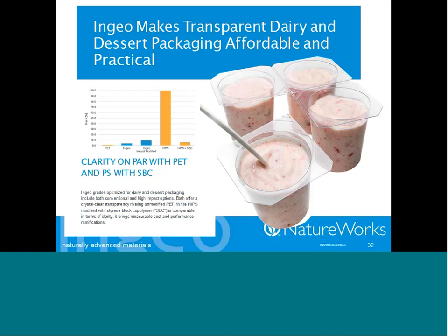A typical choice or material that's used in this sort of packaging as an incumbent would be polystyrene. So a regular high-impact polystyrene, because of the impact modifier that's in there, becomes very hazy, even though it's still amorphous. The polystyrene industry solved that issue by coming up with some styrene butadiene copolymers that are added as impact modifiers to bring the haze down. And NatureWorks or Ingeo has impact modifiers as well that will allow us to deliver very haze-free or very clear material as well.